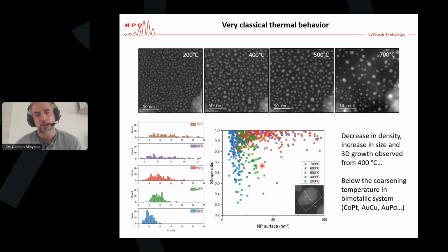And then you start heating those nanoparticles, and you realize that in fact they have a very classical thermal behavior, exactly like the bimetallic systems. You increase the temperature starting from 400 degrees, you see a decrease in the density of the nanoparticles, and you also observe a 3D growth. So your size increases, the density decreases, and you also see that the aspect ratio of the nanoparticles goes close to 1, meaning that you have a 3D growth of the nanoparticles. They become small spheres, in fact. And this starts from 400 degrees. So you see that it's even way below the temperature where you see this coarsening in the bimetallic system. I've shown you the cobalt platinum nanoparticles, but it's also true for other systems.